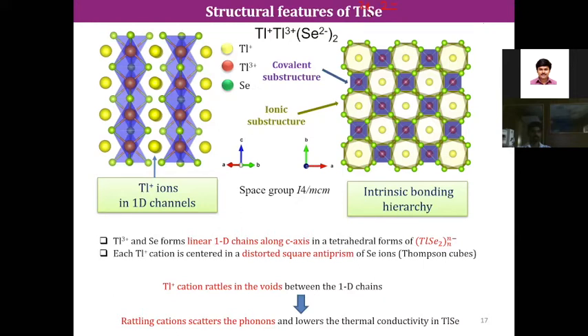Then we plotted the valence charge density. As you can see, this is the thallium plus 3, and this is the selenium 2 minus. It forms nice electron sharing. This is the covalent bonding. But thallium plus 1, which has this spherical lone pair, sits in this channel, and that can have weaker bonding, so it can rattle. And then we calculated the electron localization function, which also shows the lone pair.